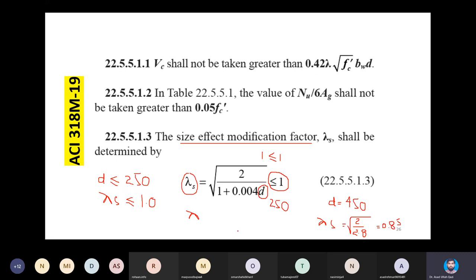to acknowledge that simply by increasing the effective depth does not mean that your VC will be amplified to the same extent, that if D is 450, VC will be of some magnitude. If D will be 650, it will simply be multiplied with 650 by 450, and whatever is the ratio for that much amount, the VC will increase. So this modification factor, which will give you answer always less than one when your D will get bigger than 250. But if your D is less than 250, you will get some answer which will be still controlled by the condition that in no case your lambda s will get value more than one.